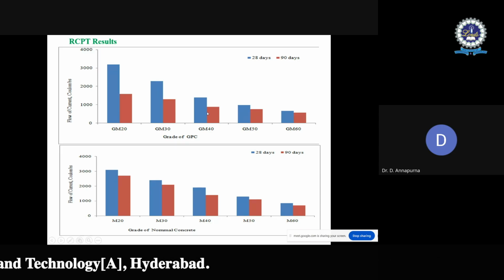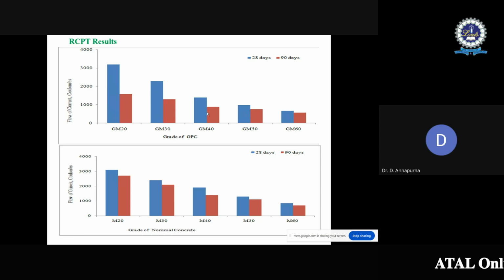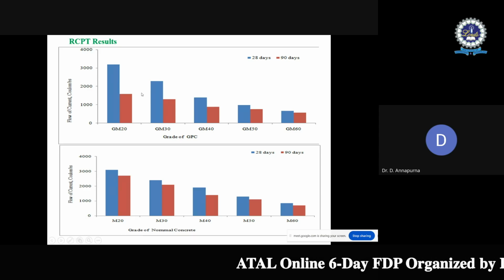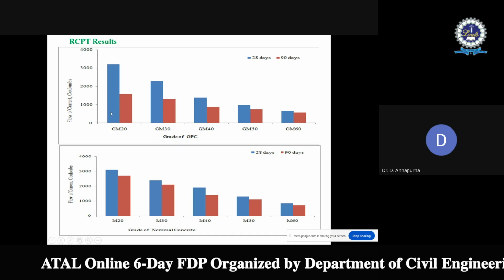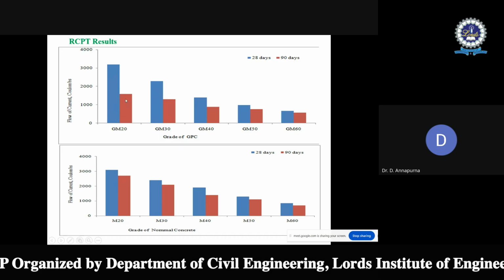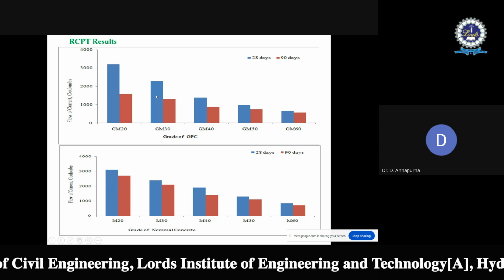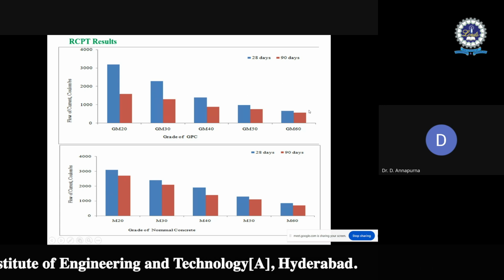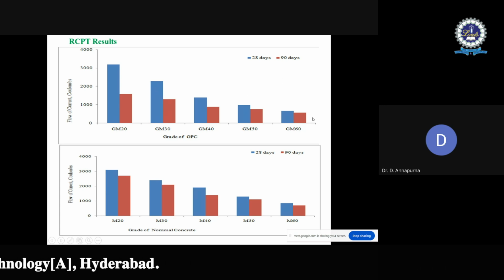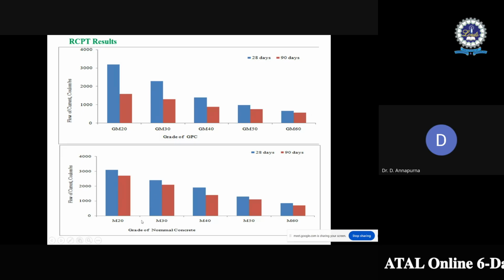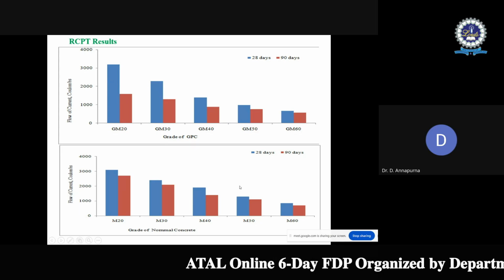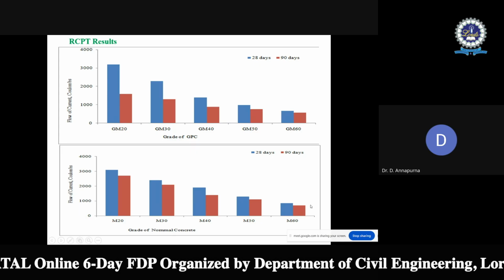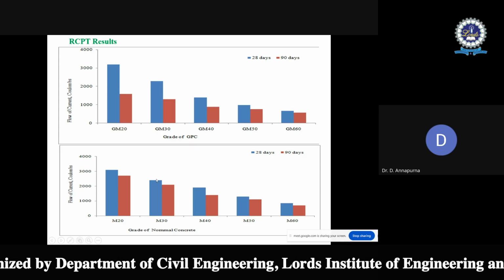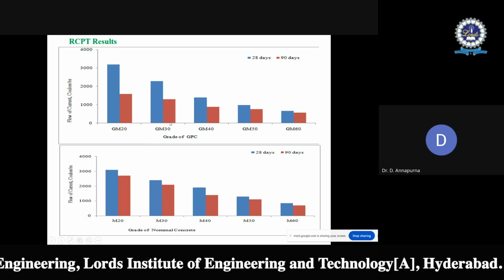Based on ASTM standards, that is ASTM C1202 code guidelines, the chloride ion permeability of GM20 and GM30 is classified as low. The 40, 50 and 60 grades of geopolymer concrete are classified as very low. Whereas in the case of normal concrete, M20 and M30 grades are classified as moderate, 40 and 50 are classified as low, and 60 is classified as very low. So almost similar behavior is observed in chloride ion permeation rate.